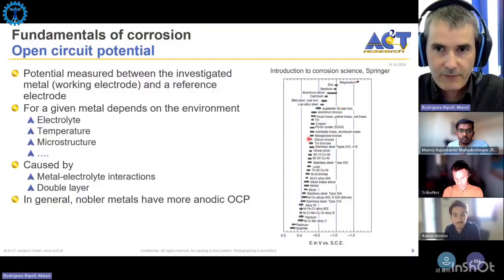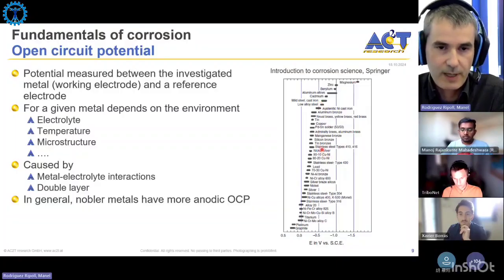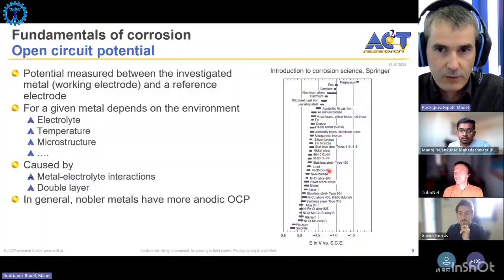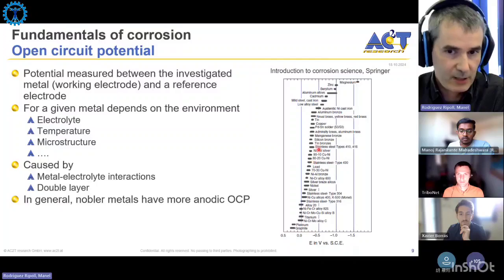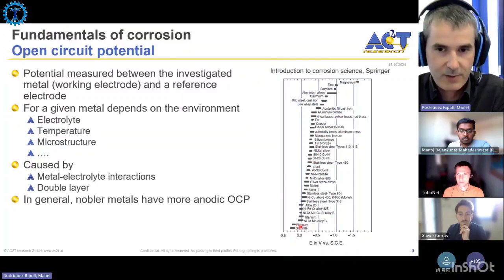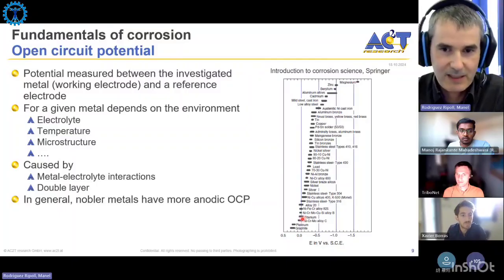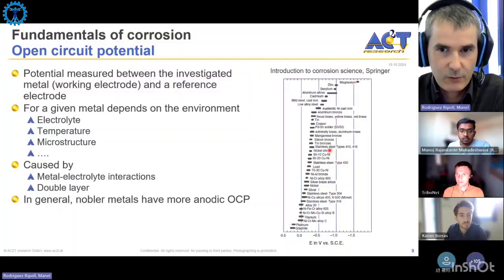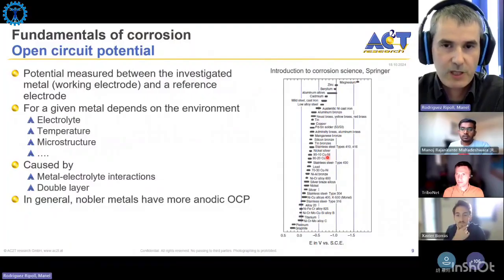It means if you get, for example, copper or steel, and you contact it with zinc, zinc will be the anode and will corrode, and by this iron, or copper, will be the cathode, and they will be protected against corrosion. But if you, for example, join iron or copper with platinum, then it will be the other way around. Platinum will be the material that is not corroding, and then the anode will be the iron or the copper. So that's important to know, that when you put a metal in an electrolyte, it dissolves, it emits electrons, and it builds open circuit potential.